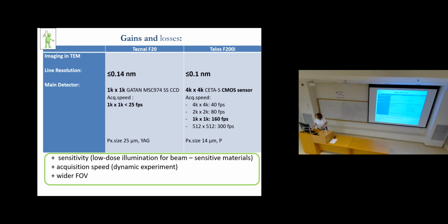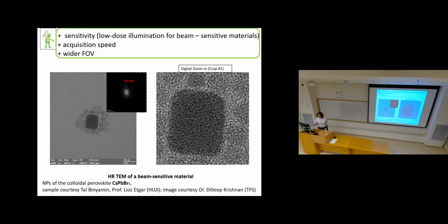And here I show you images which belong to the group of Professor Lioz Etgar. The samples were from Tal Binyamin. These images were acquired not with our instrument, but with the same instrument during the evaluation at the manufacturer lab. This is an image acquired of colloidal perovskite, cesium lead bromide. The material is extremely sensitive. It is so beam sensitive that it is not easy to acquire a single frame, so it degrades in the course of the acquisition.